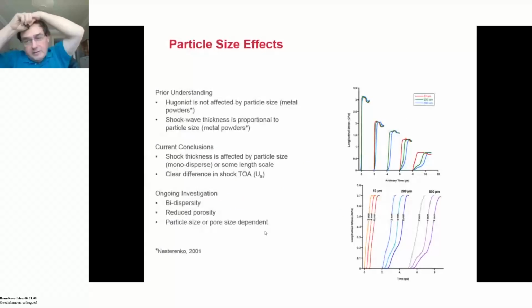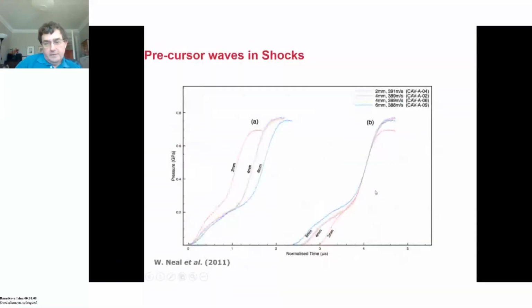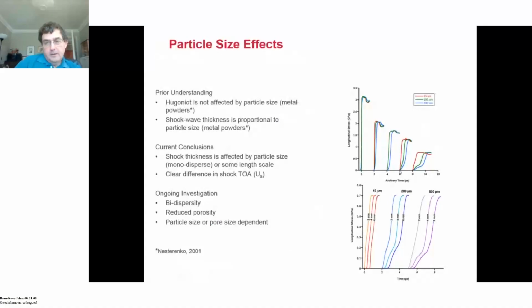If you say, well, what about the effective particle size? What we see here is the comparison of different particle sizes, and you can see the general change amongst the class of materials. 63 micron, basically, not very much changes. 200 micron, very marked change. 600 micron, really clear change in the setup of the system. So that's important. Up here, you'll see these various classes of material compared, and you'll see how they generally collapse onto one type of curve.